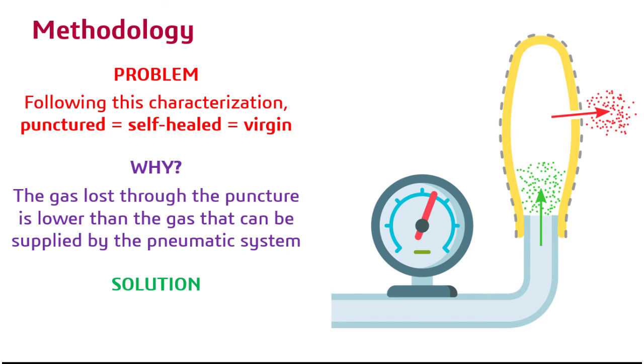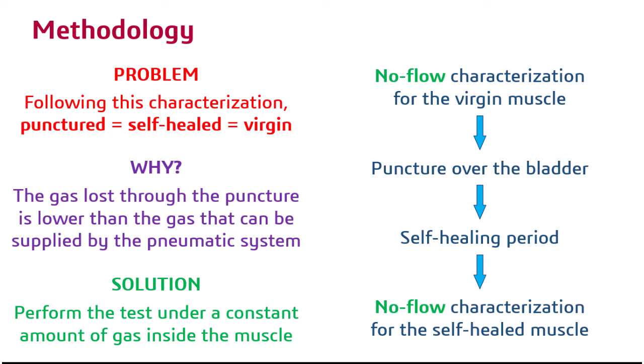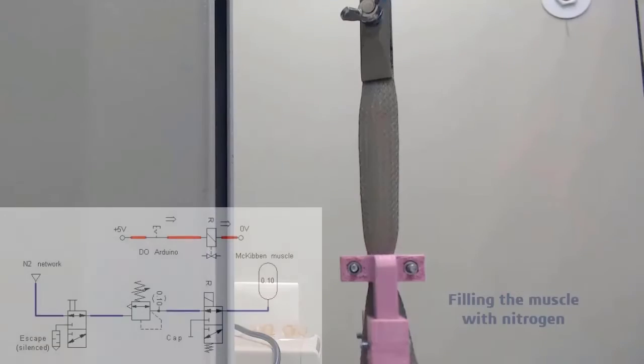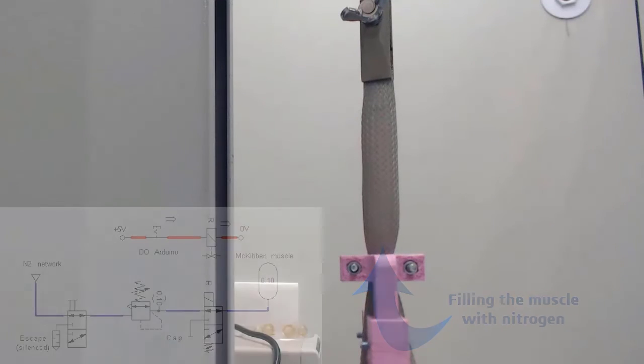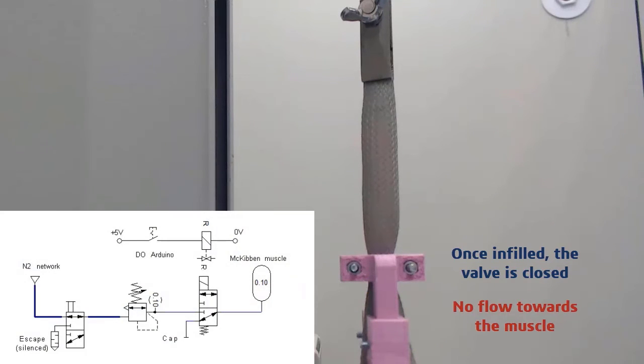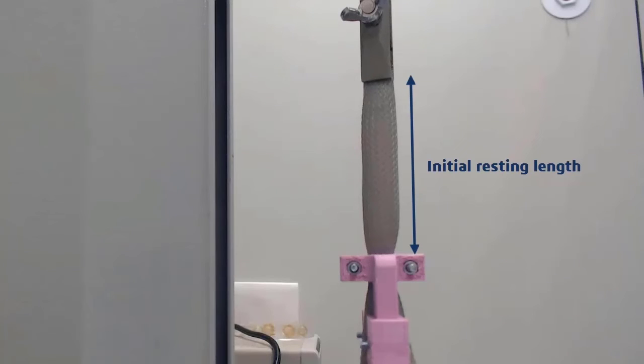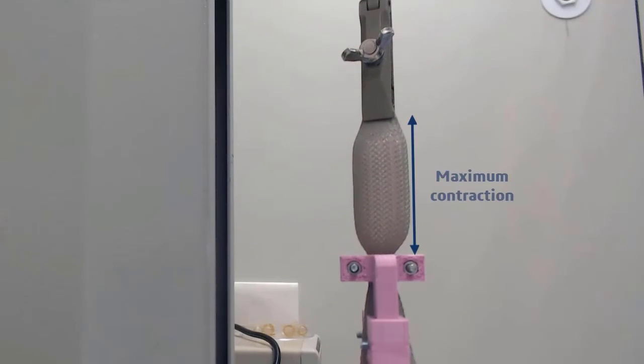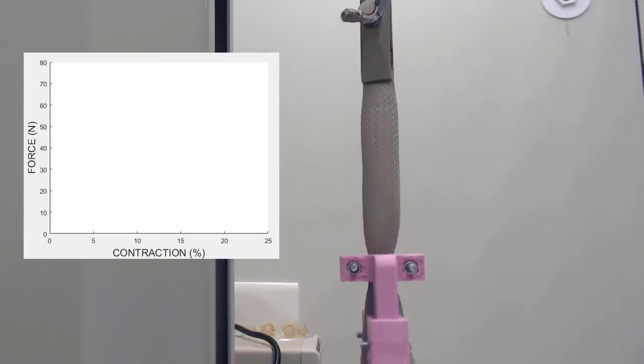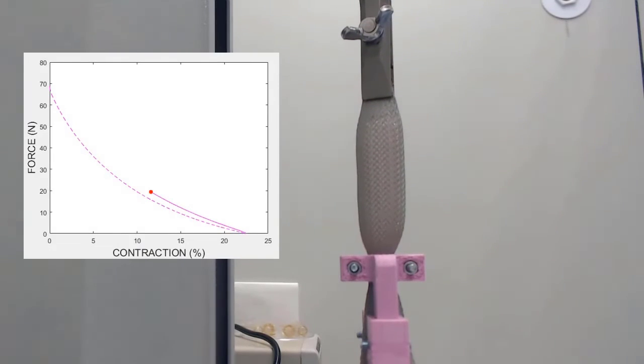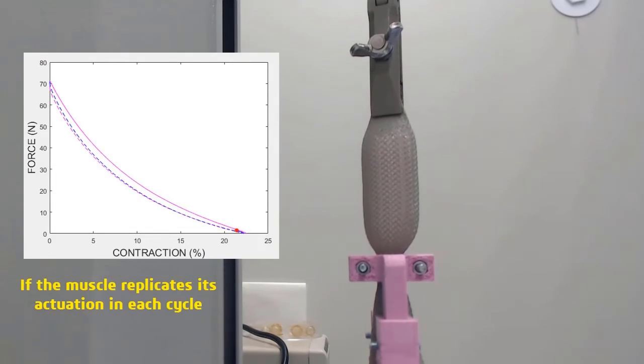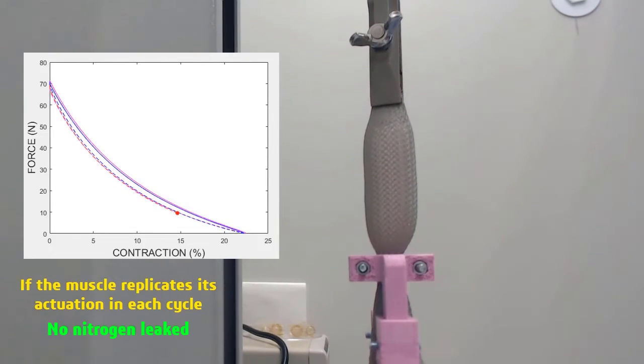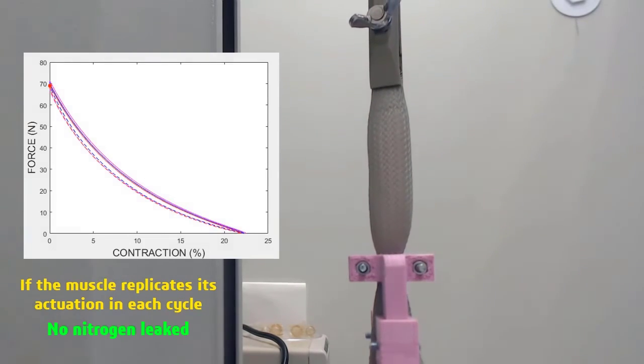The solution was using the same previous test, but under a constant amount of gas inside the muscle, which is what we've called no-flow characterization. In this case, once the muscle is filled with gas, the supplier valve is closed, so there is no flow towards the muscle. We perform the test from the muscle initial length to the point where there is no force. And we repeat this several times. If the muscle is able to replicate its performance, it means that no gas is leaked. Otherwise, if there's a leakage, it would be noticed because the muscle would not work.